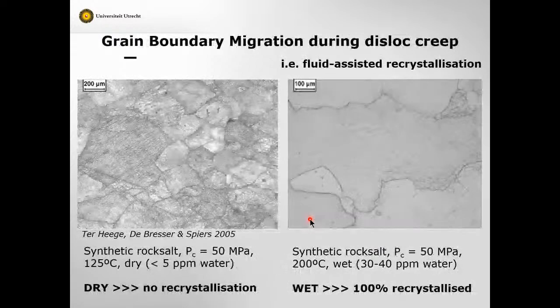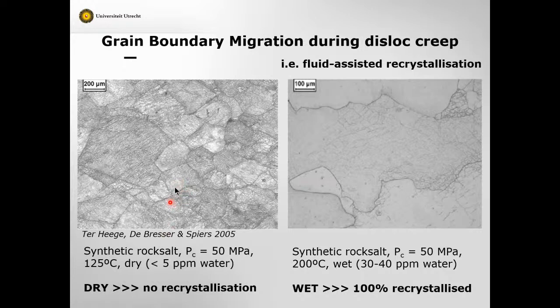That's also very important. So here are a few quick shots to give you some idea of what can happen. As well as pressure solution, you can get transport not just around crystal boundaries, but across them. This is salt deformed dry, and you see the original grains there. They're all happy doing nothing. There's been no pressure solution, no activity of fluid. There's very little water. This is dislocation creep behavior. But under the same conditions, if it's wet, you only need 20, 30, 40 ppm of water. This is exactly the same material.